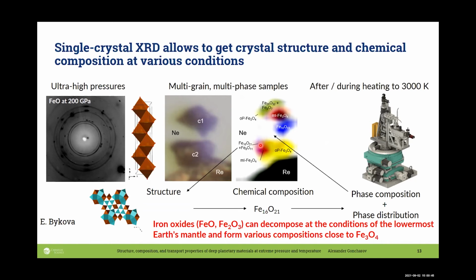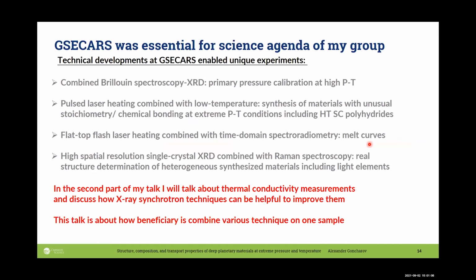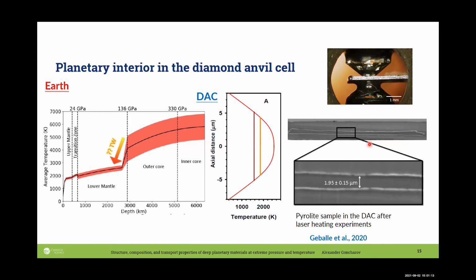And what you can see here is that if you do laser heating of FeO, for example, or if you do laser heating of Fe2O3, you can have materials of various compositions and various structures. And it's of course an advantage to have experiments where you do simultaneous X-ray diffraction and laser heating. Okay, so now I'm going to switch to thermal conductivity, and this is something which is, I believe, of interest for this audience.